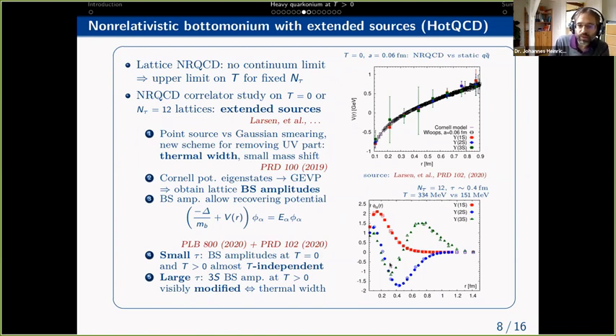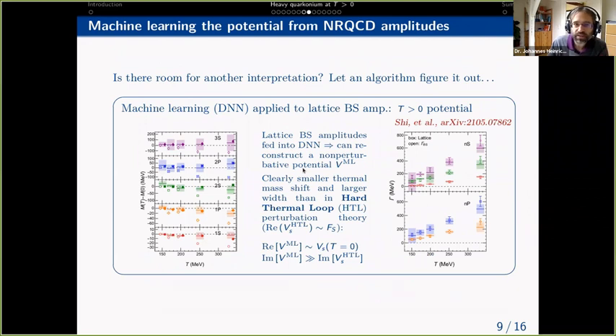And you see that these wave functions for the 1S, 2S, and 3S essentially show no substantial temperature dependence at smaller times. But as you go to larger imaginary time, you see that the 3S Bethe-Salpeter amplitude becomes visibly modified. And if it's not visibly modified at small times but modified at large times, that suggests that it should be a thermal width that is responsible, that leads to a non-stable state. Now, that's interpretation from humans.